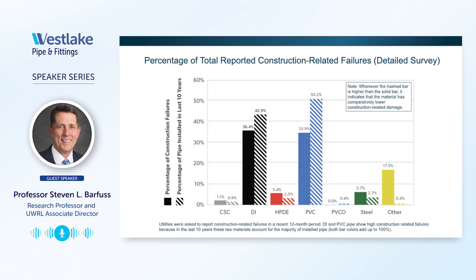This particular plot, just to change the subject here, is construction-related failures. To interpret this, let's look at this hashed legend right here. This is the percentage of pipe installed in the last 10 years. So you can see the hashed bars represent the percentage of pipe installed in the last 10 years, where all the hashed bars added up adds up to 100%. So 50 and 42% of all the pipe from the detailed survey, PVC and ductile iron, that's where the pipe was installed in the last 10 years, and the associated number of construction failures. And so if you read this note, whenever the hashed bar is higher than the solid bar, it indicates that the material has a comparatively lower construction-related damage.